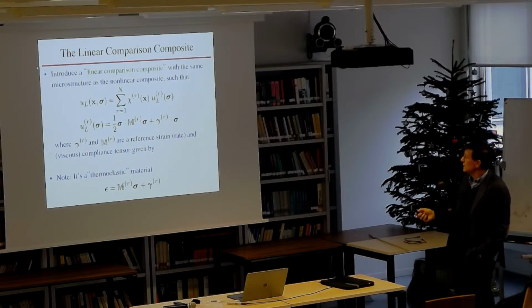So we introduce this linear comparison composite, which has the same microstructure as your nonlinear one. So this is just for one realization of the material. But the stress potentials are quadratic in the stress, and they depend on some viscous compliance if you're doing viscoplasticity, and some eigenstrain rate, or if you like, strain rate polarization. Because when you differentiate this with respect to the stress, this is the constitutive relation that you get.